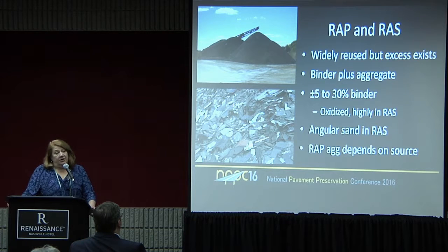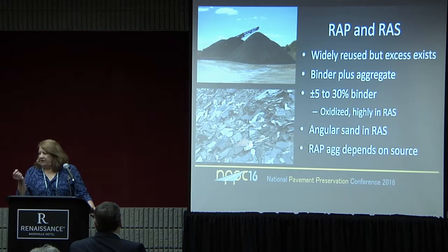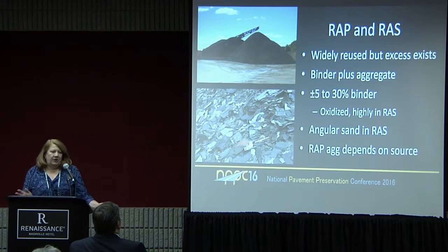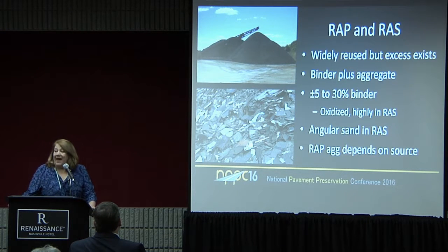And one advantage of shingles in some places is the aggregates that are used are very angular and hard. So again, coming from a place where even our gravels and our sands are mostly carbonates, those are good sand-sized aggregate particles that we can use. Of course, what kind of aggregate you have in your RAP depends on the source. And I'll give you an example here in a few minutes of where a county was able to take advantage of a much better aggregate than they normally would get by using RAP.